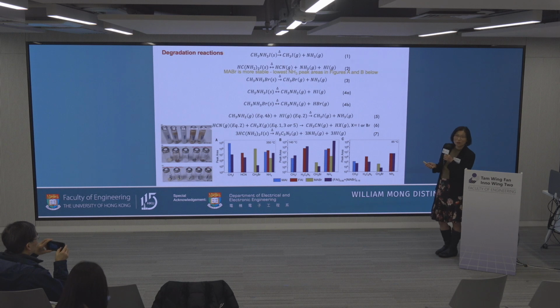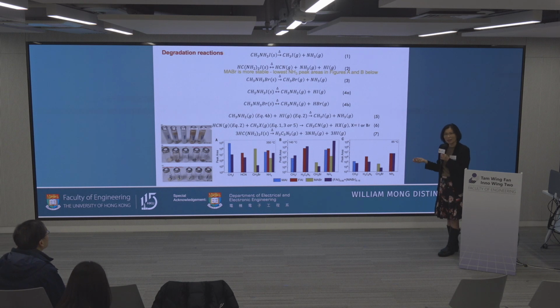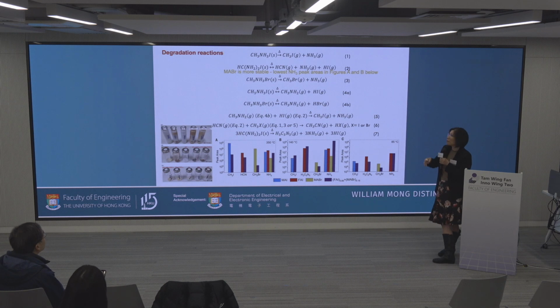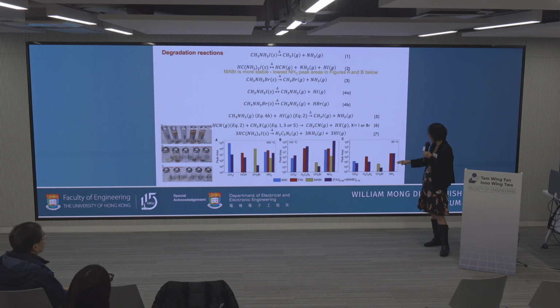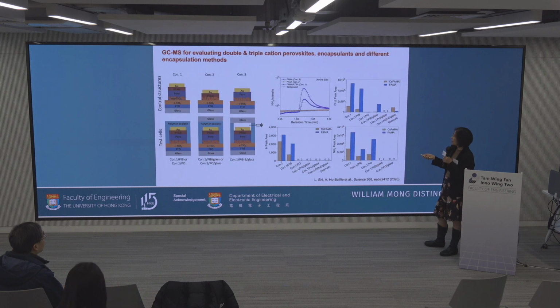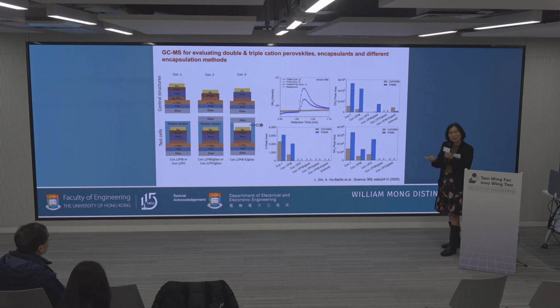Okay, so we also knew that MABr was more stable, looking at Professor Siok's solar cells, but here we can confirm that using GCMS, where if you have MABr, it has a lower NH3 outgassing. So that's really good work. We also looked at what happens if you put cesium into cesium MA-FA perovskites. And in fact, even if you have MA, in the presence of cesium, the outgassing is 5 times lower.